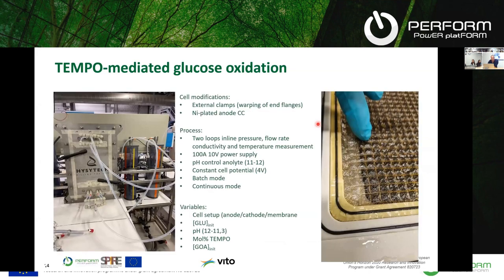Some of the practical issues may be important to note also, things that we see, because of course upscaling involves the introduction of a lot of practical problems. So one thing was that there were some leaks, let's say, at the initial stage due to the fact that the end flanges were warped a little bit when it was assembled. This was adjusted by using external clamps to provide sufficient pressure on the center part of the cell. Another thing is that we nickel plated the anodes to prevent passivation of the current collector there.